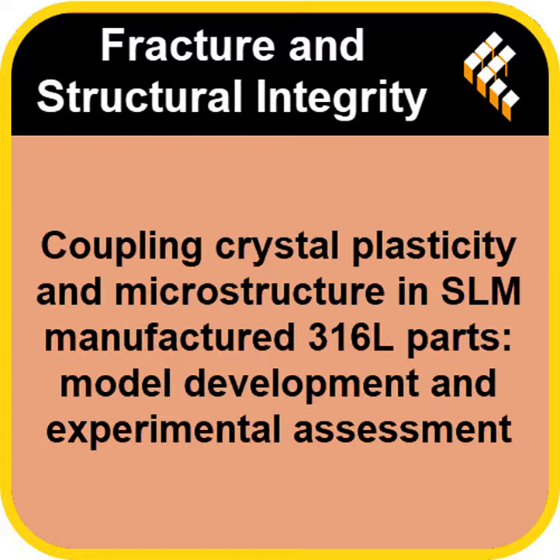And to understand that, we have to talk about something called stacking fault energy. Okay, let's unpack that. Stacking fault energy. That's basically the material's preference for how it deals with stress, right? Does it slide cleanly, which is slip, or does it form these little internal defects, which is twinning? That is a perfect way to put it. 316L has a very low stacking fault energy. This means it has a low tendency for that standard slip, but a very high tendency toward twinning. Twinning creates a kind of mirror image of the crystal structure across a boundary, and it's an incredibly effective way to harden the material. So a normal piece of steel might deform by sliding. This SLM steel deforms by twinning.